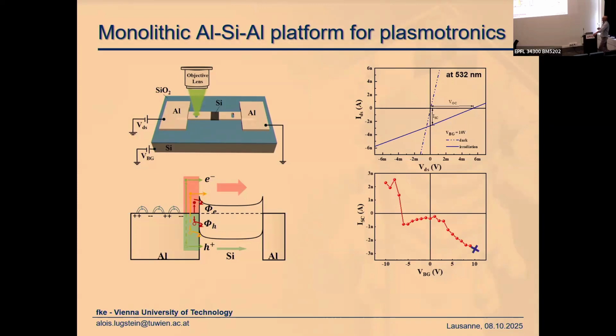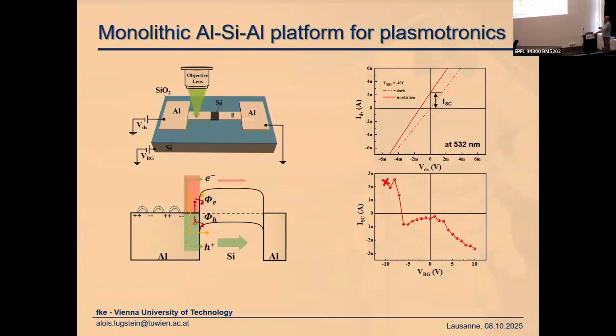Anyway, if you change the backgate, you will bend the bands either downwards or upwards. And if you apply a positive gate voltage, you will bend it downwards, and that means you will block the holes, and you will preferably inject the electrons, and that means we detect a negative current. Even at zero bias, so for an unbiased device, you measure a negative current through this device, which is just a result of the injection of charge carriers with the momentum in this direction, and they will surpass this silicon segment. If you change the backgate voltage to negative backgate voltages, you will bend the bands upwards. Now you block the electrons, and you will preferably inject the holes. So we detect a positive current. Again, even at zero bias, you see a positive current.